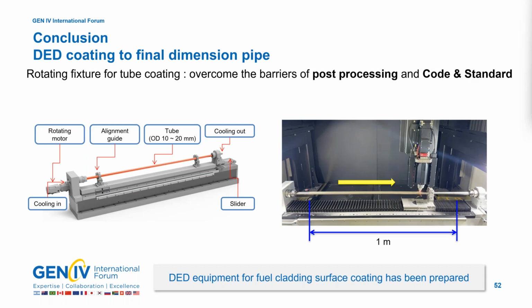The results obtained so far are meaningful as they were achieved using a plate substrate. However, they differ from the process of coating the outer surface of a tube, which is the ultimate goal of this study. Therefore, to achieve this final objective, we have developed a rotating fixture for tube coating, enabling a final coating length of 1 meter on the outer surface of the tube.